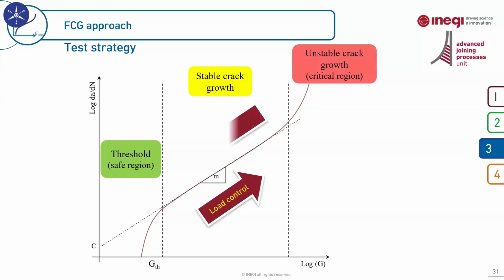As we discussed earlier, the Paris law consists of 3 main regions: threshold region, stable crack growth zone, and finally the unstable crack growth part. And we have 2 different strategies to analyze the fatigue crack growth in adhesive joints. The test can be load control or displacement control. In load control, the test starts from a threshold region. Then we move to a stable crack growth part, and then finally the joint fails with an unstable crack propagation. In displacement control, the test starts with an unstable crack propagation. It moves backward to stable crack growth, and finally we reach a threshold region. And when we reach the threshold region, the crack propagation stops and the joint doesn't fail.